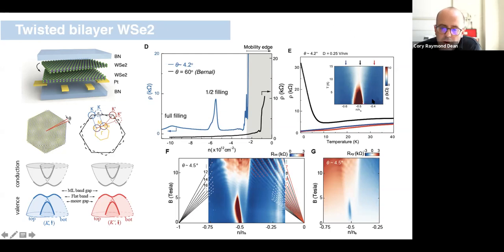And here in the top right, all I'm really identifying is that indeed, if we look at the temperature dependence at this half filling position, then that looks very much like an insulating state. It's not just that we have a resistive peak at low temperature. It really has an insulating-like temperature dependence. And as I dope slightly away from there, I transition from an insulating-like temperature dependence to a metallic-like temperature dependence on both sides.